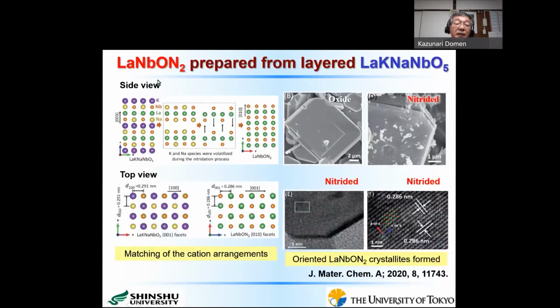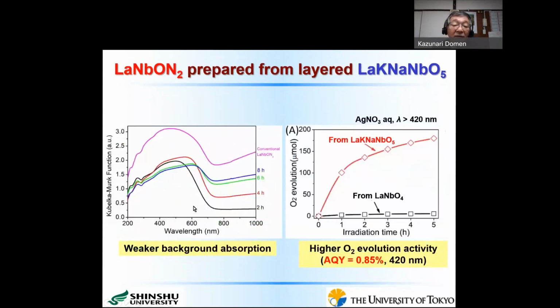In this case, we prepared lanthanum niobium oxide nitride from lanthanum potassium sodium niobium oxide materials. The reason to use this precursor material is that the cation arrangement is very similar to our lanthanum niobium oxide nitride, as shown here. And this is the precursor oxide material. After nitridation, as you see here, these are atomic-scale resolution TEM images, and they are very well crystallized. Then we examined the activity and absorption spectrum of these materials.